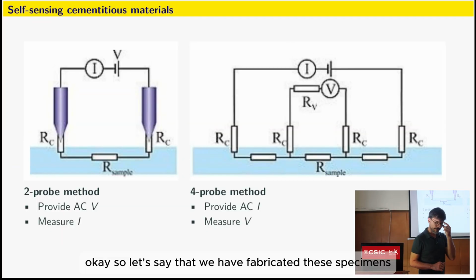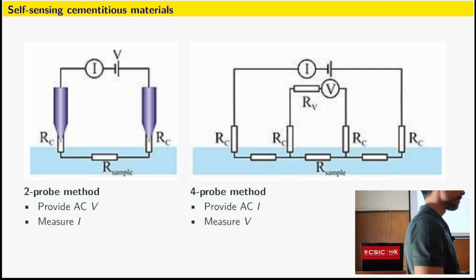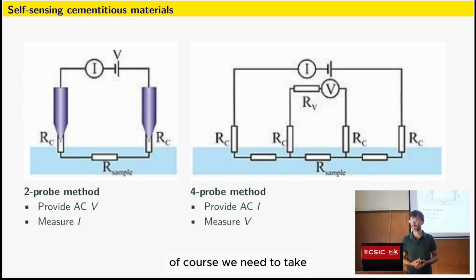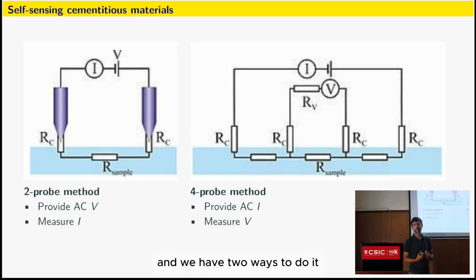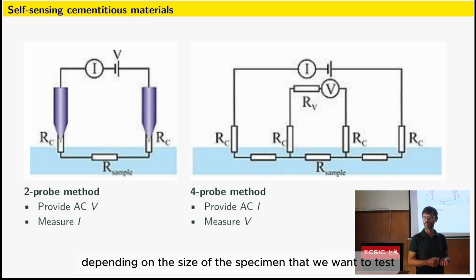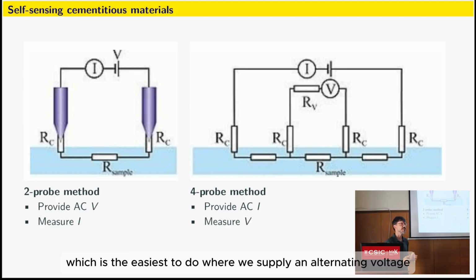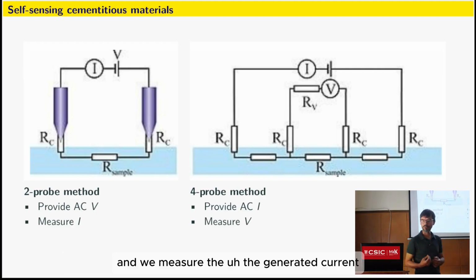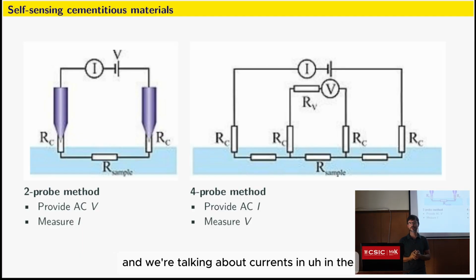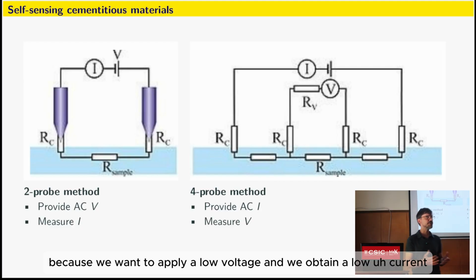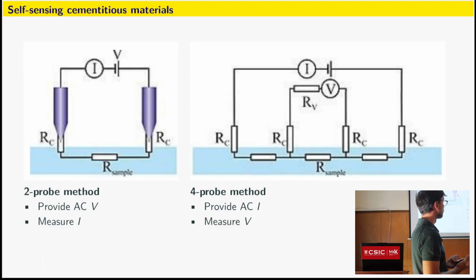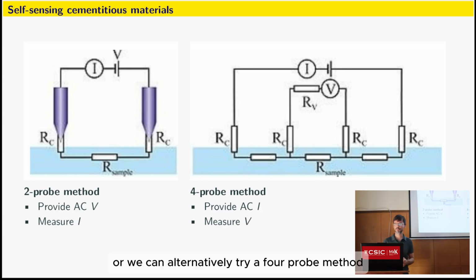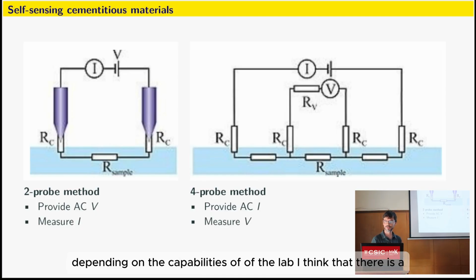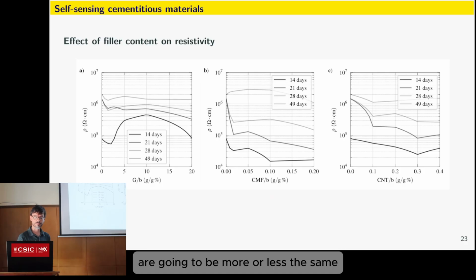Okay, so let's say that we have fabricated these specimens. Of course, we need to take electrical measurements in order to determine the resistance. And we have two ways to do it, depending on the size of the specimen that we want to test. We can either do a two-probe method, which is the easiest to do, where we supply an alternating voltage and we measure the generated current. And we're talking about currents in, I don't know, the microampere range, because we want to apply a low voltage and we obtain a low current. Or we can alternatively try a four-probe method. This is just depending on the capabilities of the lab. I think the results are going to be more or less the same.